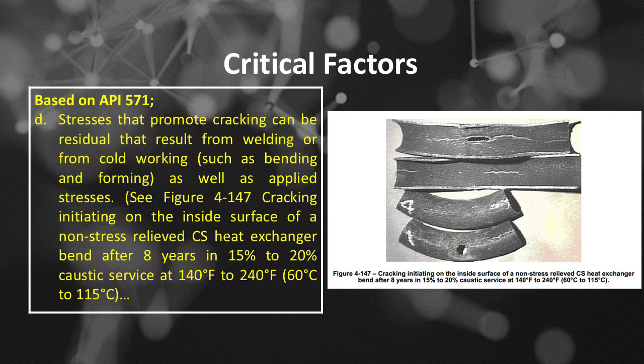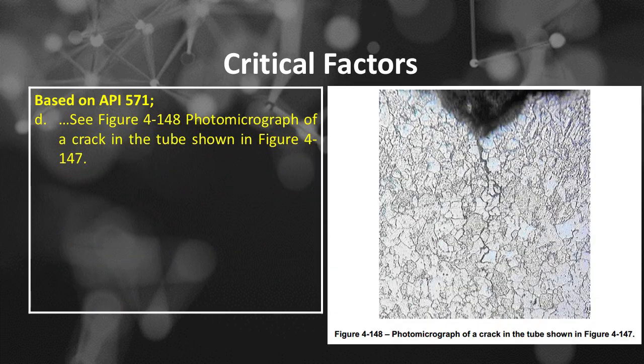Cracking initiating on the inside surface of a non-stress relieved carbon steel heat exchanger bend after 8 years in 15% to 20% caustic service at 140 degrees Fahrenheit to 240 degrees Fahrenheit, or 60 degrees Celsius to 115 degrees Celsius. See Figure 4-148, photomicrograph of a crack in the tube shown in Figure 4-147.